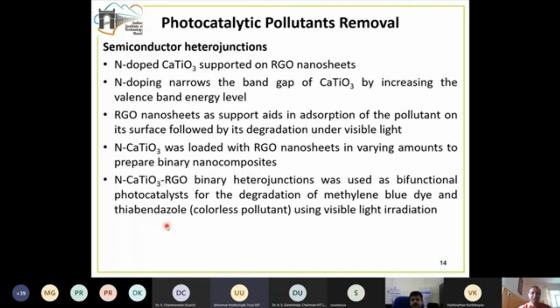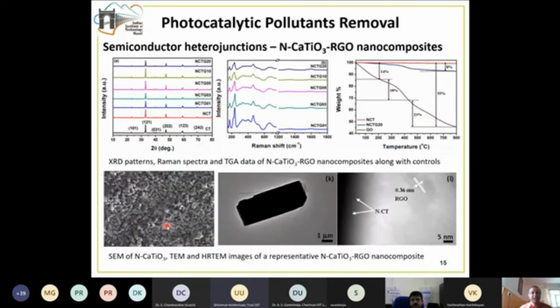And similar to the previous work, we did a detailed characterization of this material using X-ray diffraction, wherein we did it for simple calcium titanate, the N-doped calcium titanate, and the N-doped calcium titanate with varying amounts of reduced graphene oxide, ranging from 1 weight percent to about 20 weight percent. We also did Raman spectroscopic investigations. We also did the TGA, thermogravimetric investigations.